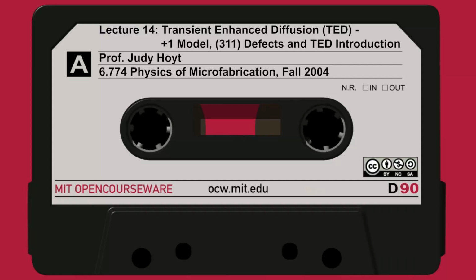And then after 10 minutes, look how far the boron has gone. The boron profile has gone quite a ways. The junction depth now is about 0.4 microns. So that's the red profile, solid line. And the dashed line here, you should also reference that to the right-hand axis. The interstitial supersaturation ratio is now down. Instead of 10 to the 4th, it's 10 to the 2. It's about 100 after 10 minutes because we're getting rid of more 311s, and eventually the number of them is going down. So this thing only lasts so long.